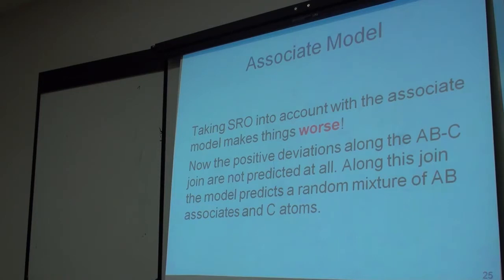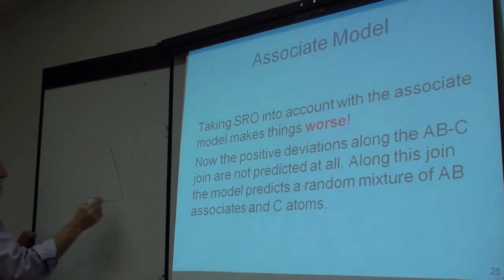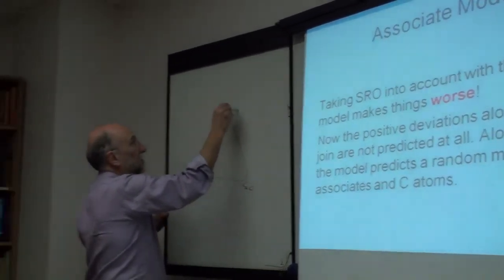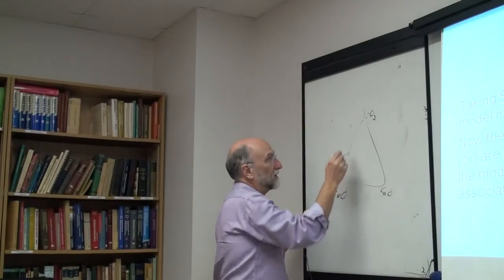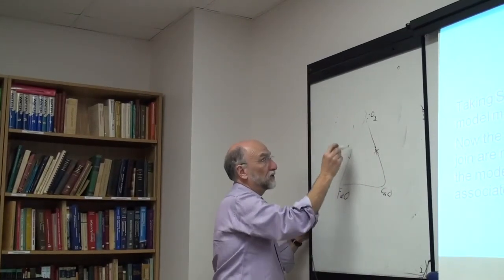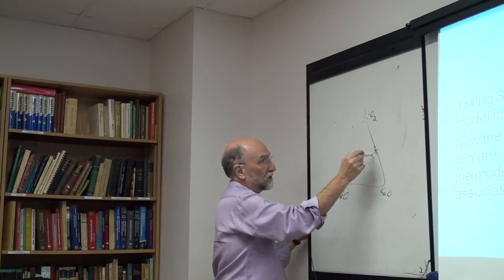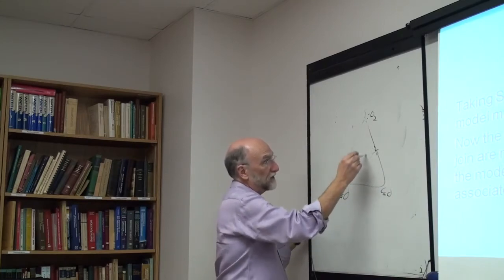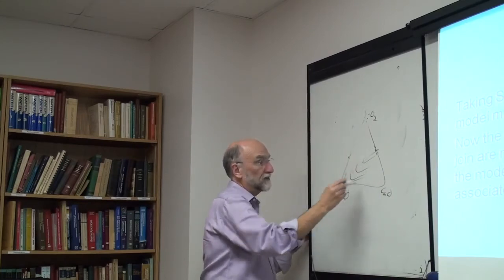The trouble is in the oxide system, since we've used Z equals 2, you don't get any miscibility gaps. If you take something like the calcia silica FeO system, this is highly short-range order. This is also short-range order, but not so much. So along this line, you're getting these positive deviations with your liquidus curves that come out like this.